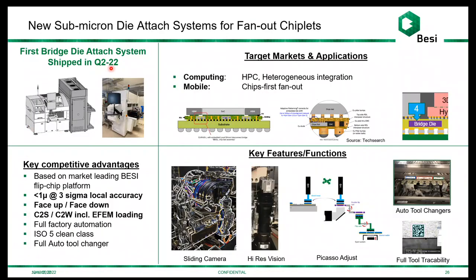To enable this application, we've introduced a new system we call the Cameo Ultra. And basically this provides the ability to place die in a face-up configuration onto a substrate with sub-micron accuracy as well. And we do that with another new, really innovative alignment system that uses a clever method of recognizing the location of the die front and back at the same time without slowing down the machine. So we can achieve a 5,000 UPH sub-micron placement die face up, really optimized for fan out and bridge attach.